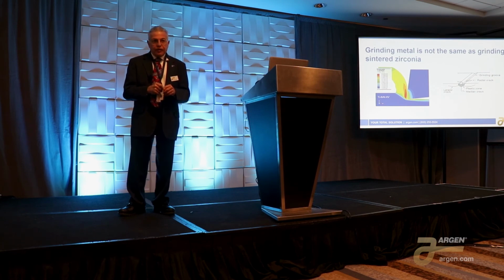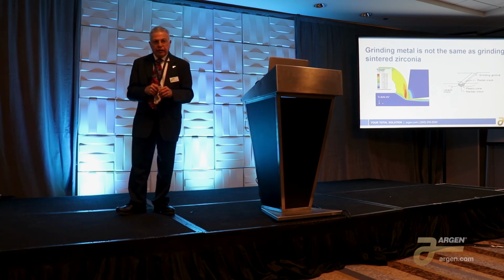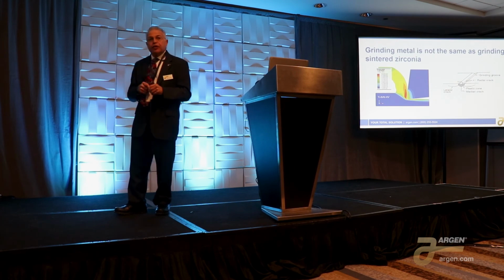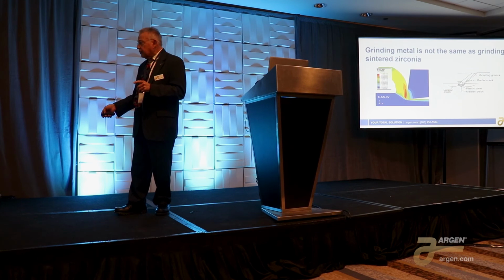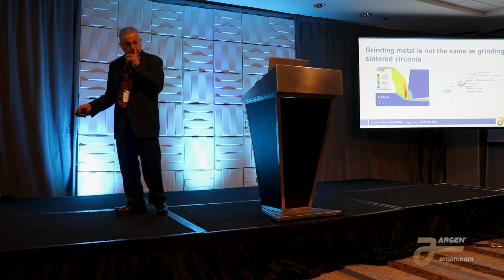It's not curling off. It's not being processed off like porcelain. It's actually being chipped off. And the biggest danger is you form this median crack. The median crack will always be at 90 degrees to the score of the diamond.